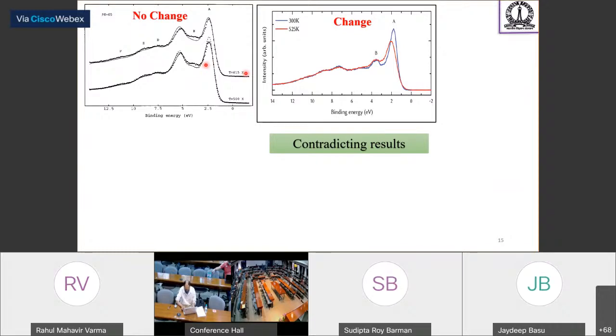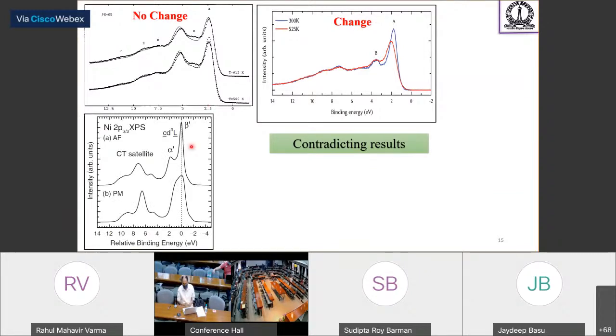So far we have two experimental reports. One is showing no change, and another one is showing change in the valence band spectra. And one theoretical result shows a prominent change in the core level spectra. But both of these experiments have been done using photon energies which are very surface sensitive and can see the surface electronic structure only, which is possibly different from the bulk electronic structure. This point gets even more critical when we are doing high temperature measurements, because at high temperature, there is a chance that some of the oxygen may leave the surface of the sample.